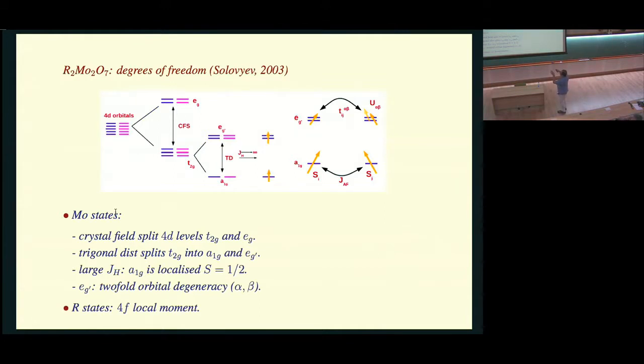So we will be quick on this. Unlike the parent Hubbard model, which had one orbital with electrons hopping between sites and a local correlation, this has a deep level which behaves like a magnetic moment. So the effective degrees of freedom on the molybdate are not just one orbital with up and down spin, it's basically a deep level, a so-called A1G level, which behaves like a magnetic moment, essentially localized, and an orbitally degenerate EG prime state up here.